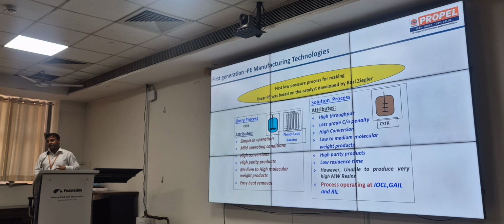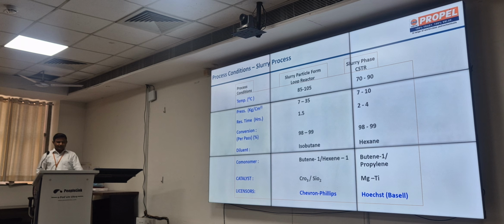At IOCL, we have a 300 kTPA plant at Panipat where we are producing LLDPE and HDPE grades. Different processing conditions: temperatures in the slurry loop reactor versus the CSTRs are 80 to 105 and 70 to 90 degrees centigrade. Pressure is similar, slightly higher in the loop reactors. Residence time, which is very important, is 1.5 hours in the loop slurry reactor and 2 to 4 hours in the CSTRs. The conversion is similar.